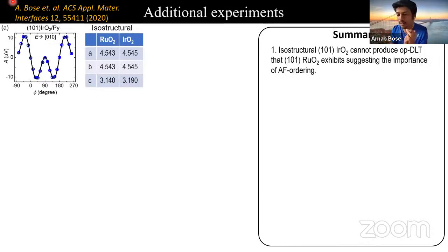Okay, so now we provide some other experimental evidence. For example, what if it is not related to antiferromagnetic ordering, but something related to the crystal structure? So we checked it by comparing iridium dioxide and ruthenium dioxide, because they are isostructural, their lattice constants are very much the same, and the quality of the sample and the strain, everything is very similar in iridium dioxide and ruthenium dioxide. But we do not observe any extraordinary torques in the same iridium dioxide plane, meaning the bulk crystal structure is not enough. We need the Néel vector, or we need the spin split bands.